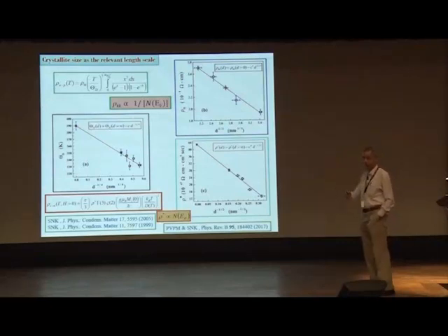When you decrease the size, the surface area is increasing, and so is the surface disorder. Because of that, the density of states curve is getting more and more smeared out, so the density of states at the Fermi level is getting suppressed. The sharp peaks in the density of states near the Fermi level are getting leveled off, so the average density of states at the Fermi level is decreasing.